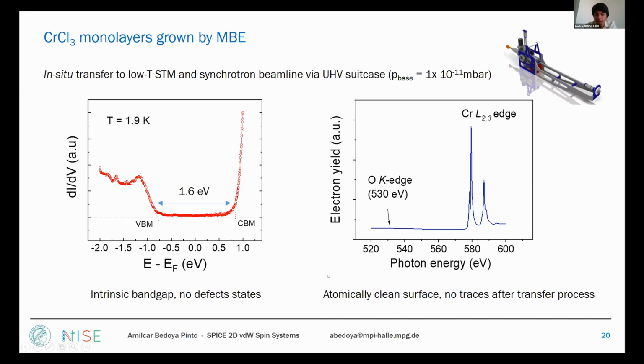And when we went to the beamline, of course, we wanted to see the chemical integrity of the surface before starting the magnetic measurement. And here we see the oxygen K edge is completely absent, and we have only the chromium absorption edge. That's actually very good news, because that means that there is not even any impurity on the surface. So we are probing really the pristine monolayer chromium chloride.